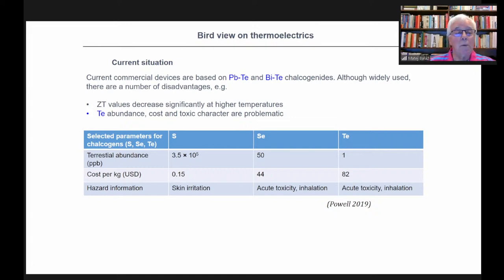In this table, I wanted to show you, for example, the terrestrial abundance of these chalcogenides. If you compare sulfur with tellurium, you see how big the difference is between these two elements. And of course, the cost per kilogram in US dollars also shows a big difference. Look here: for sulfur, $0.15, for tellurium, $82. The problem is also with hazard, because while sulfur gives some small skin irritation, contact with tellurium is toxic and very harmful in case of inhalation.